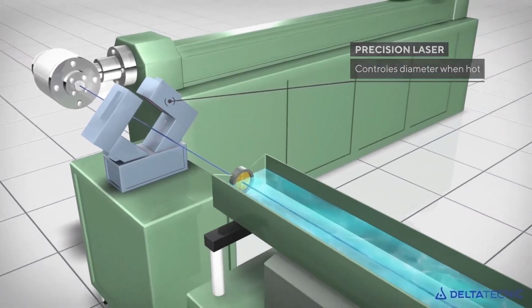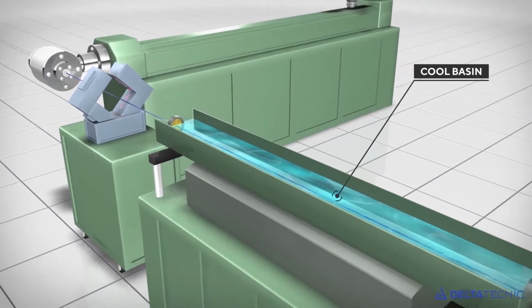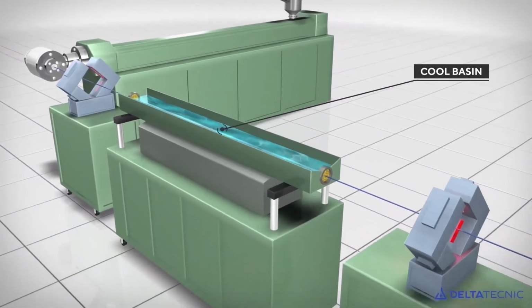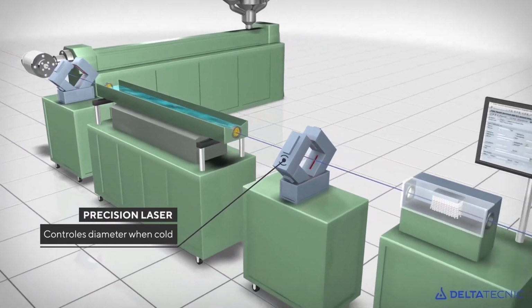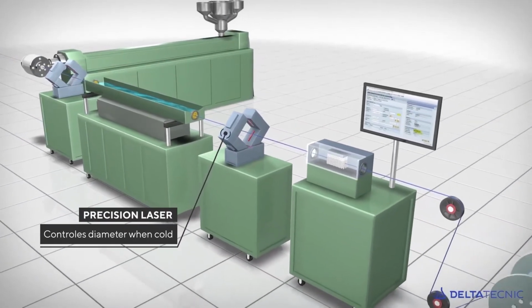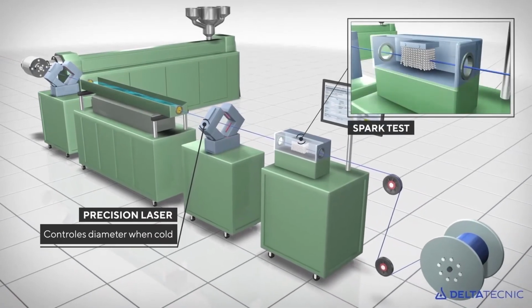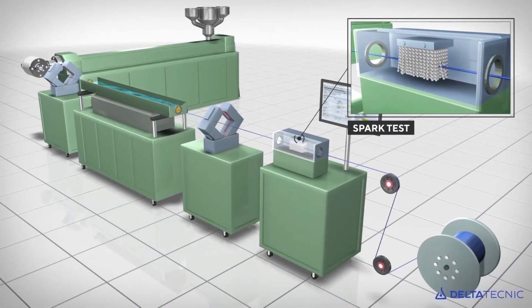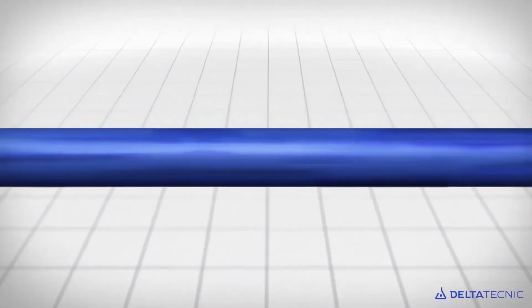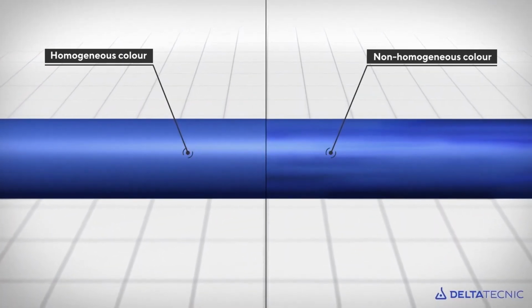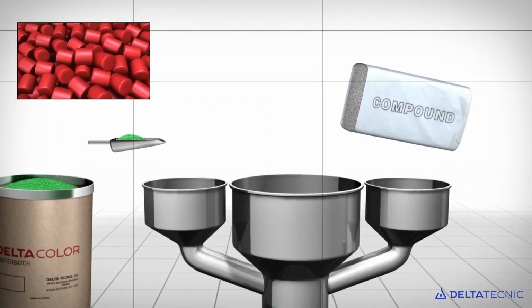But basically what we're explaining here is that if we go to faster extrusion lines, into faster cable manufacturing processes year after year, at a certain point, we don't have enough time for the color to melt and to incorporate homogeneously into the extrusion process, and therefore we produce a cable whose surface presents these lines, this non-homogeneous color, this color irregularity. And that's the problem. And sometimes that's the problem, not always. Sometimes with some colors, and I will go into that later with the case studies.